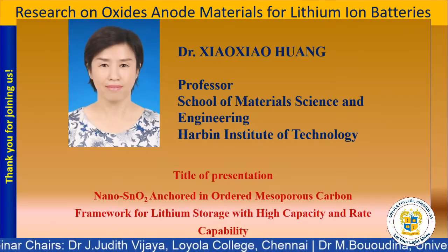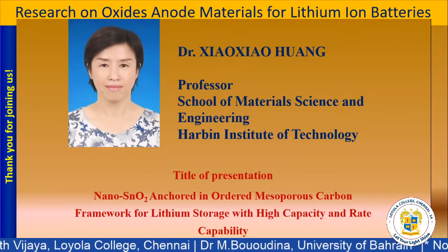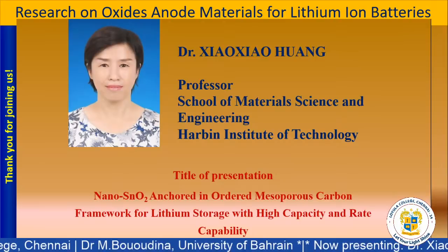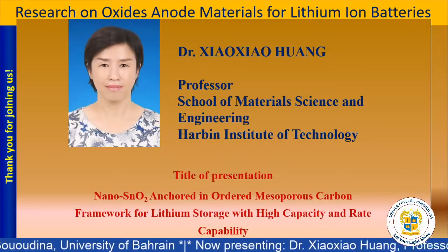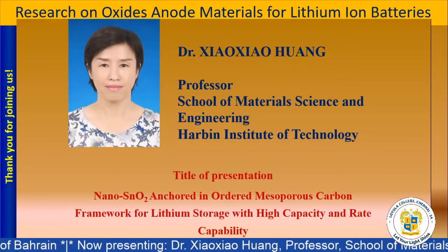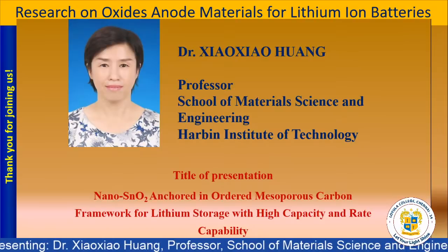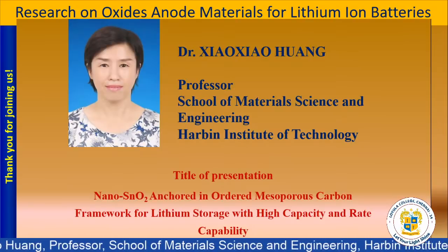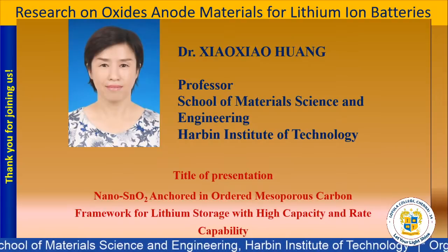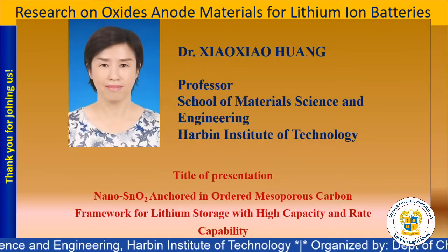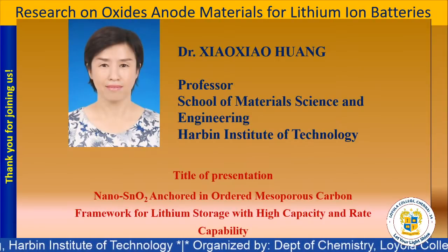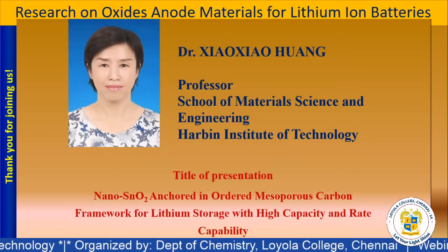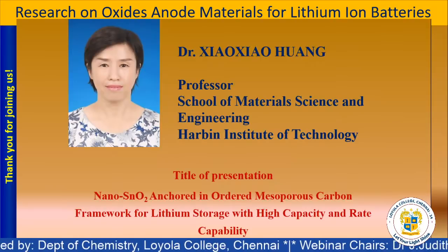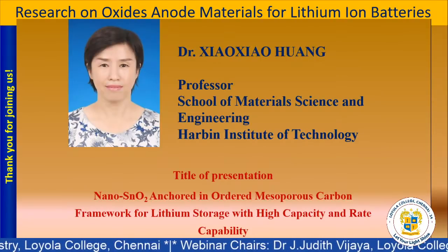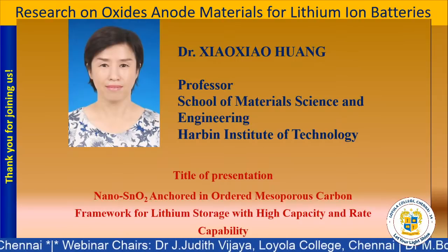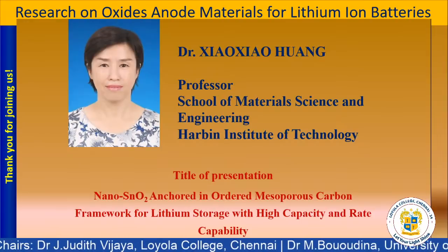I didn't introduce it in detail because you can notice that the temperature is lower. It's only below 500, for the ultrafine size. We used the precipitation process method to prepare it before, but the size of the tin oxide will grow quickly. So if we want to get a very good crystal structure, when we get the crystal structure, the size will be bigger. So it's not okay.